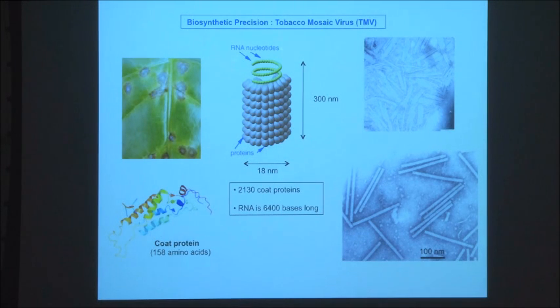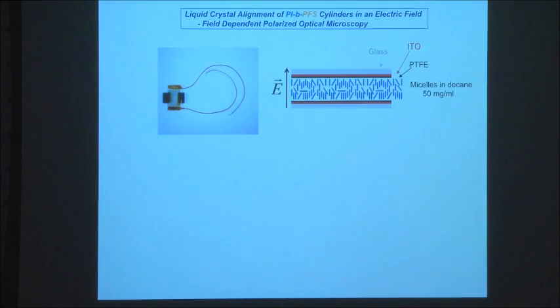But if you want to make tobacco mosaic virus with different lengths, if you don't want 300 nanometers, then that's a tough job. You've really got to do some synthetic biology to do this, and it's not a trivial matter. Whereas the block copolymer self-assembly method, crystallization-driven self-assembly, is a very easy method to use to control the structure. So you can make structures all the same length, and this allows us to start looking at the properties of monodispersed samples of cylindrical micelles in solution.